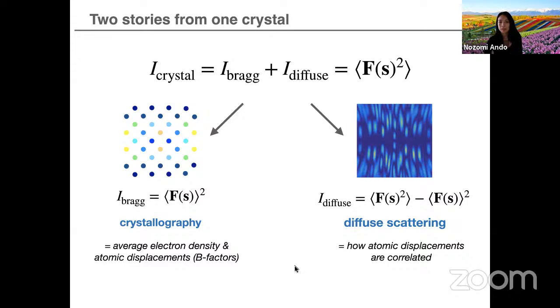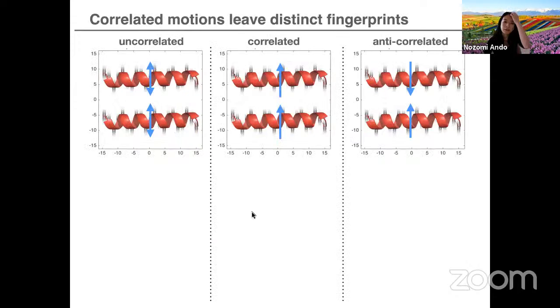But just to illustrate again why the diffuse scattering is a useful signal, here I'm showing a simple simulation that Steve did of a pair of identical alpha helices that are undergoing some kind of displacement. The displacement is the same amount, except with different kinds of motion in each case. So in these three cases, the B factors will be exactly the same. So by Bragg diffraction, we can't distinguish these scenarios. But if we simulate the diffuse scattering, then we actually see different patterns.